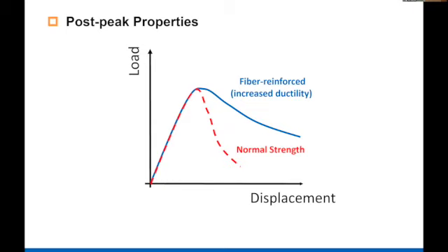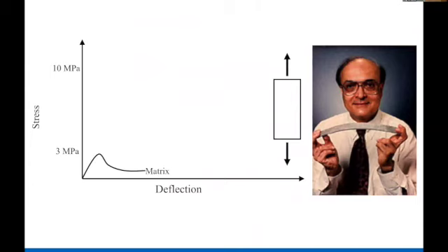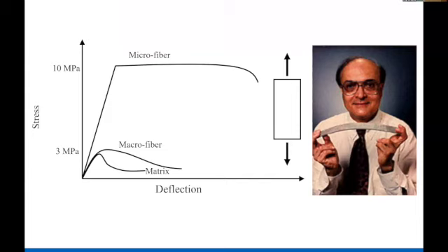But then we said, why don't we use fibers at the micro scale? And so here I'm showing you in tension the response of fibers which are at a micron scale. This, for example, were 14 micron diameter PVA fibers, about 2% of volume. And you can see that we have now increased the tensile strength because fibers can interact with microcracks and have strain hardening response. So this was the work done in the 1990s, and you can see that the material is almost like rubber, very, very flexible. And so now people are calling this strain hardening cement composites or UHPC. And as you know, quite a bit of work is done now in applying this concept.